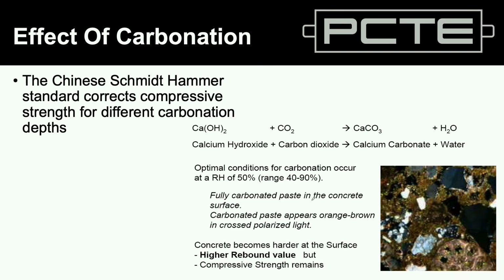Couple of limitations on Schmidt hammers. It's a surface measurement. It relates to hardness. So what if we had a way we could make the surface harder? That would be carbonation. So we'll talk about carbonation during our corrosion session this afternoon as well. But effectively what happens if you leave a porous piece of concrete out in the air for a long, long time, it will absorb carbon dioxide. That will have a couple of effects. It'll make it slightly more acidic, lowering its pH value. But what is more important for our purposes is for the same pressure to break it, the same compressive strength, the surface will become harder. So if we do a Schmidt hammer test, it will overestimate the strength.